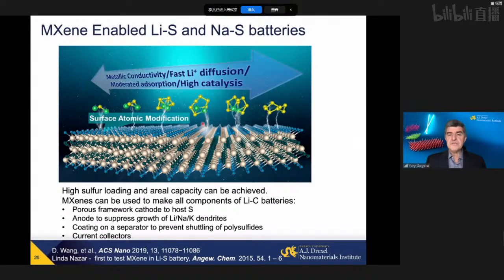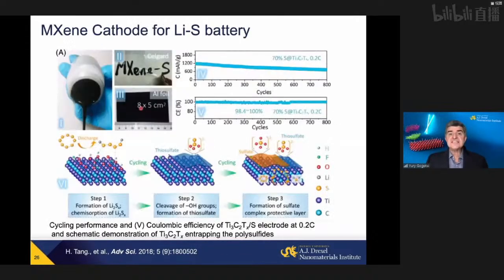They can also be used as films and separators to prevent polysulfide transport to the anode, and also as support for lithium or sodium growth on an anode, replacing copper or aluminum here. And you can see, for example, stable cycling of a battery. This is not our work, it is a published result with MXene electrodes and very good Coulombic efficiency over about 800 cycles and moderate loss of capacity here.